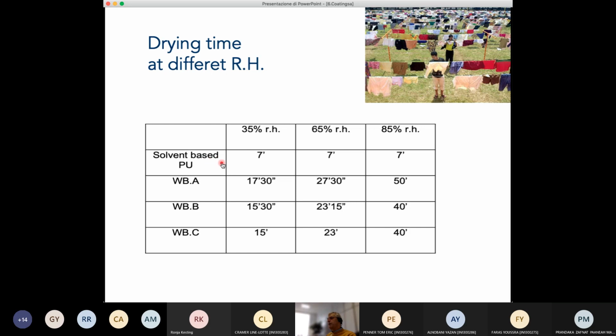Here you see some data of an experiment we carried out in my institute some years ago. The first is a solvent-based coating, and we measured the drying time with 3 different relative humidities, always at 20 degrees. And the time you see here is always the same, so there are no effects on the drying time for solvent-based coating, 7 minutes in all cases. If we use water-based coatings, we did the experiment with 3 different coatings.